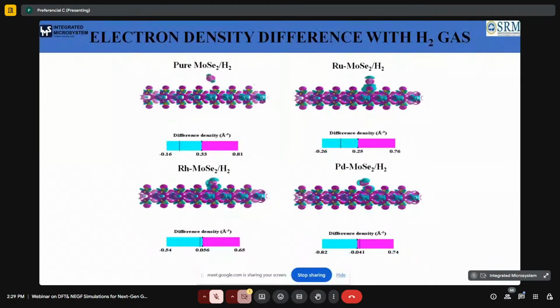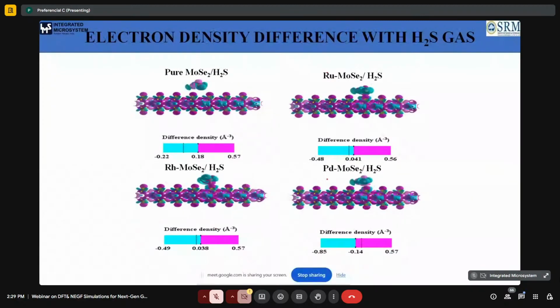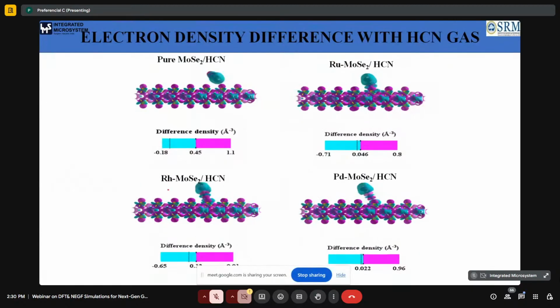And these are further analyzed by means of electron density difference analysis. In the electron density difference analysis for hydrogen gas, we can see a very slight accumulation and depletion, which implies a very weak interaction has happened between the gas and the system. But for H2S gas, visually we can see a strong charge accumulation and depletion, which implies a high adsorption and large charge transfer in the system. For the HCN system, donor-acceptor interaction is clearly seen with the dopant, and these analyses visually validate our adsorption energy as well as the charge transfer.